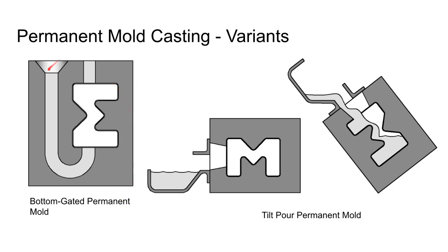There are different ways of getting the melt into the mold. A bottom-gated arrangement fills from the bottom. The key goal in any arrangement is to minimize turbulence — when liquid metal flows in a turbulent way, it dissolves gases which come out of solution during solidification and create porosity. A bottom-gated arrangement might give better results than tilt pour in some cases, or vice versa.